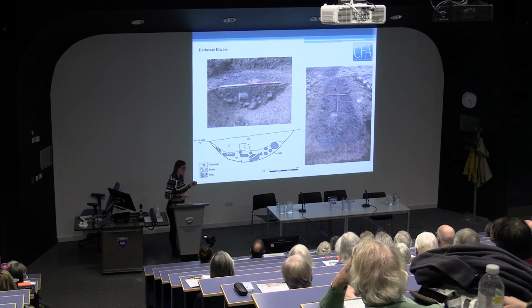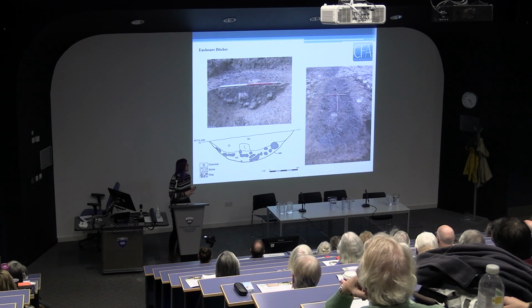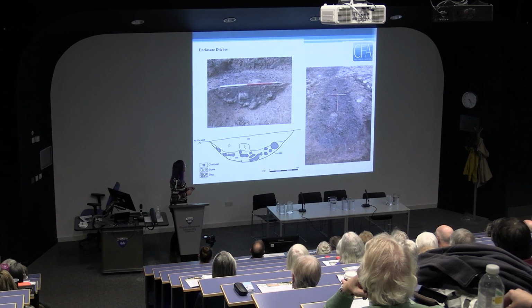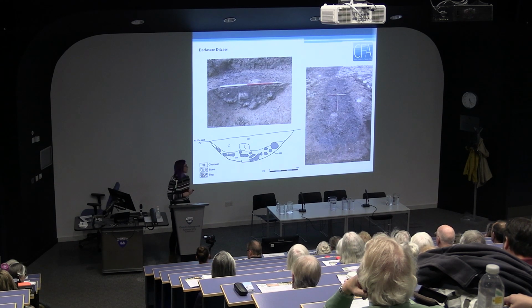Now, the main thing we found was the ditches. This turned out to be 2 suboval segments and a longer linear inside the excavation area, as opposed to the many segments that we thought we had during the evaluation. Ditch 1, which is in all 3 of these pictures, was just under 5 metres long. We dug 3 slots into it, and this was also the ditch where the vast majority of the slag recovered from site was found. You can see it here in the lower fill, and also all the large group images